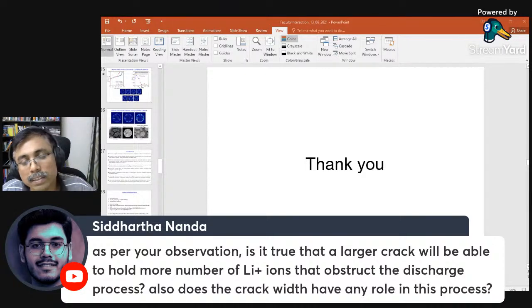Okay. First of all, a crack is not always a problem in a lithium-ion battery. We saw that a silicon anode system cracks within very few cycles, and still it retains capacity. So the question is how the crack develops. If the crack is radial, let's say for a particular composite type of cathode, and you are extracting radially, then there is not much problem, so there can be a little capacity fading. But if the crack is perpendicular, say at a particle interface that is obstructing the path, that is the main problem in that scenario. That will give you much more capacity fading.